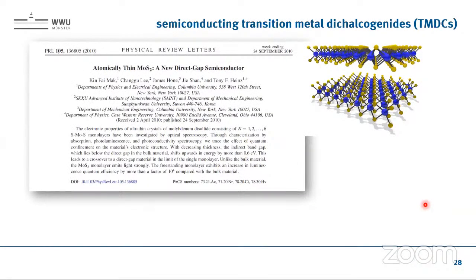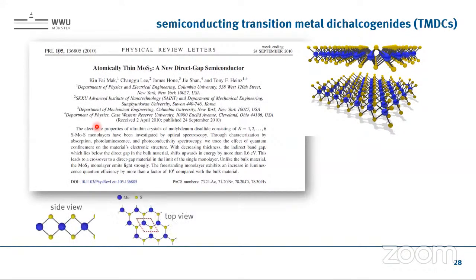I mentioned that in 2004 graphene was isolated, and the field of 2D materials got another momentum in 2010, where the group at Columbia of Tony Heinz, first of all, identified an atomically thin direct gap semiconductor. Another publication came up almost at the same time in this direction by another group, and they studied exactly this molybdenum disulfide, a transition metal dichalcogenide, where we have a hexagonal arrangement of a metal, molybdenum, and then the chalcogen, sulfur.